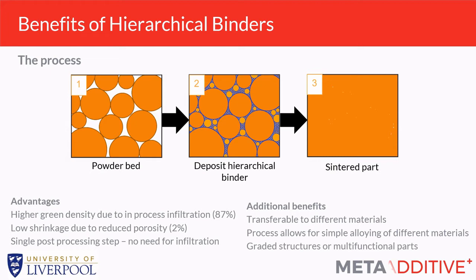So that's very high. And as a result, because you're not removing any components from the powder bed, you're actually infiltrating it with build material, the printed parts we've got with the best shrinkage rates is around 2%. So that's a massive difference and a big improvement on conventional binder jet printing. But I think the beauty here is the added benefit: because you've got build material from the inkjet head and you've got build material coming from your powder bed, we can start to print multi-materials in one printer, because that binder could be one material and the powder bed could be one material.